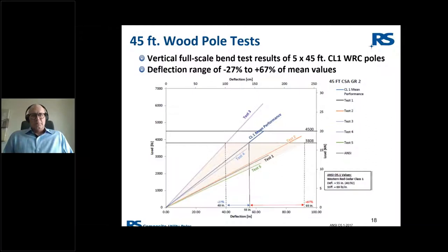So let's look at how some actual wood poles tested out when put into a vertical test fixture instead of a horizontal test fixture. All of the other attributes of ASTM D1036 have been followed, and we tested a series of wood poles from 45 up through 55 feet with five specimens at each length. So when we put these five 45 foot class one Western red cedar poles in the full scale tester, we had a deflection range of -27 to +67% of the mean values.